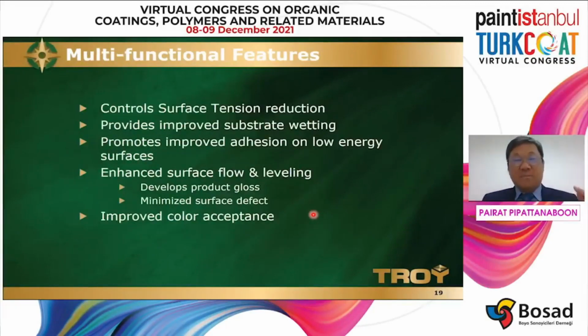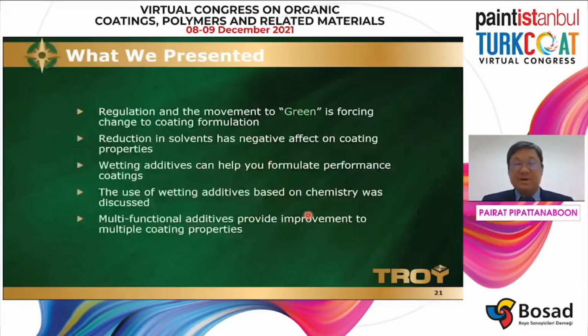The summary of the multifunctional wetting additive: the features are control of surface tension reduction, providing improvement of substrate wetting so that you get surface flow and leveling. Improve your product gloss after tinting. Also, you get color acceptance, minimize your surface defects, and in some applications like contaminated surfaces, you help adhesion on low energy surfaces. The green tendency of this technology of coatings needs reformulation latitude for that, so you reduce solvent, right?